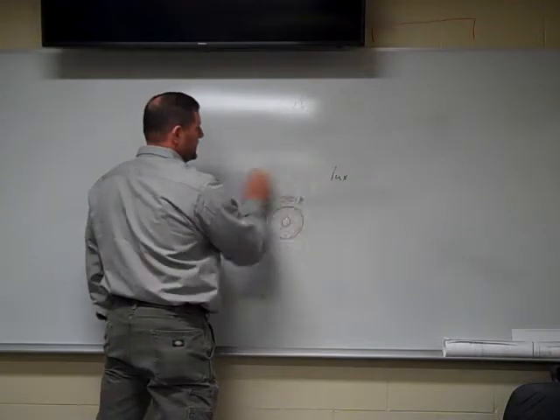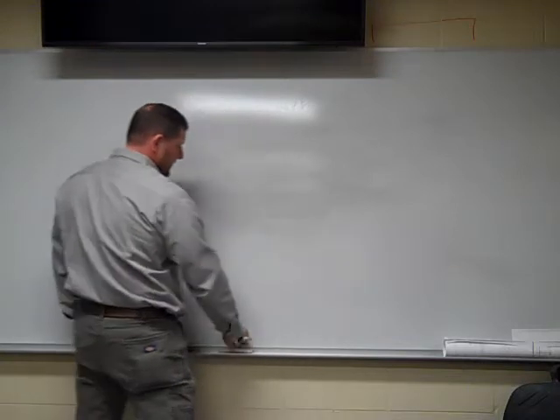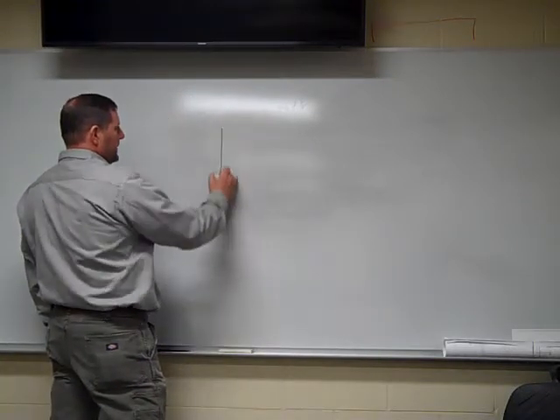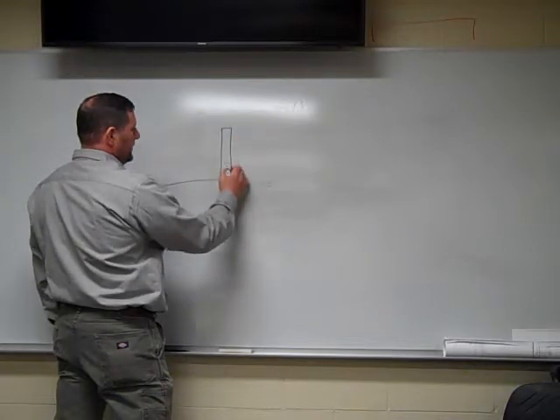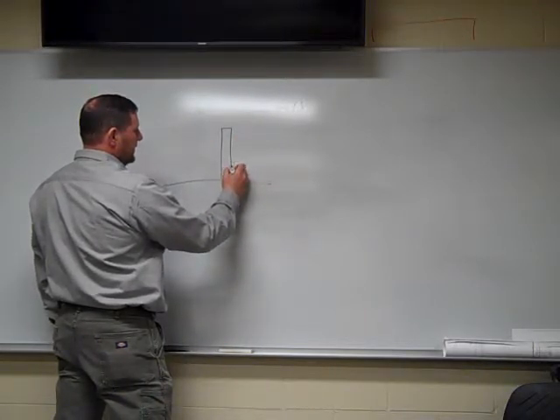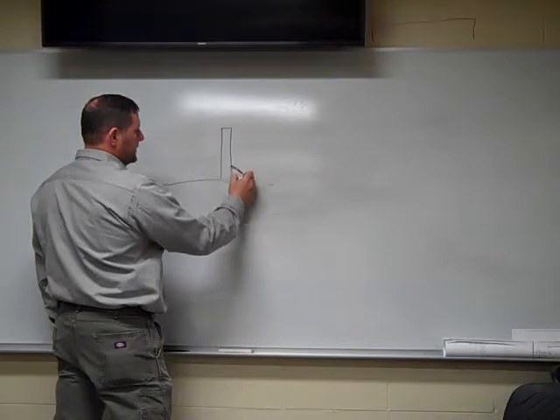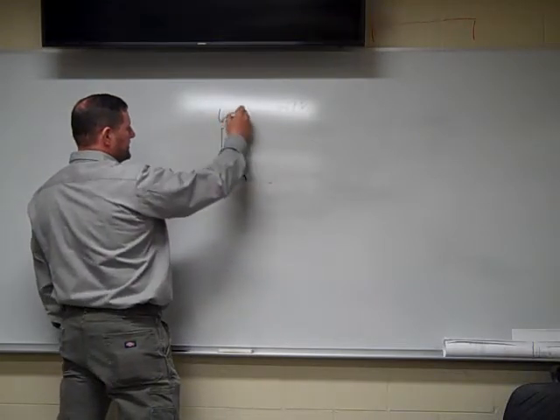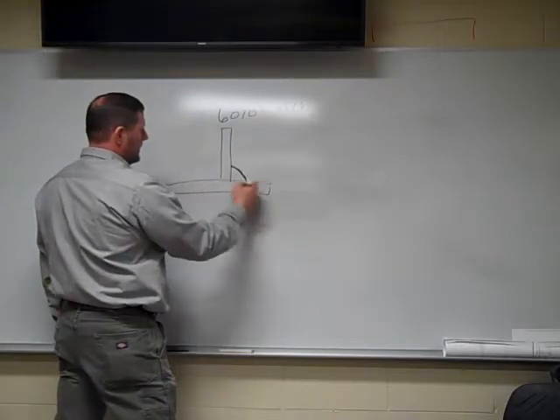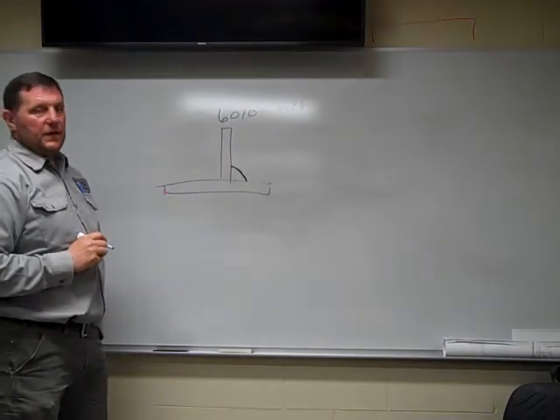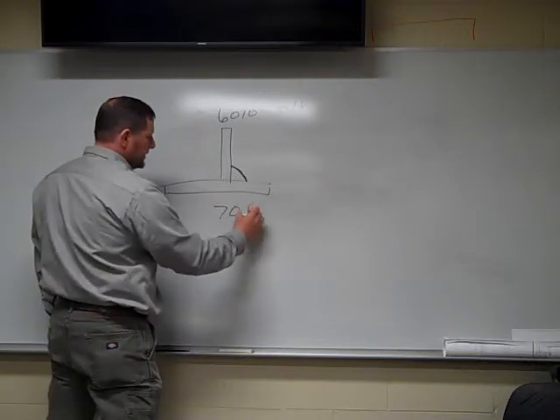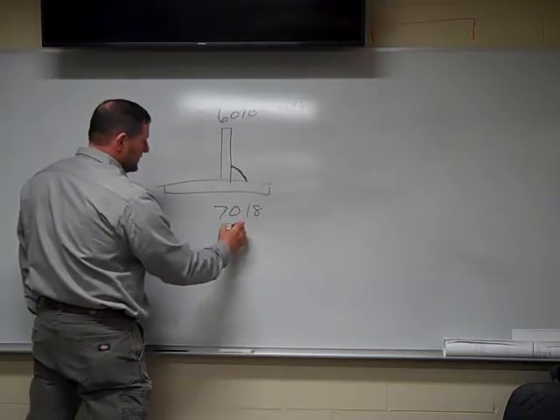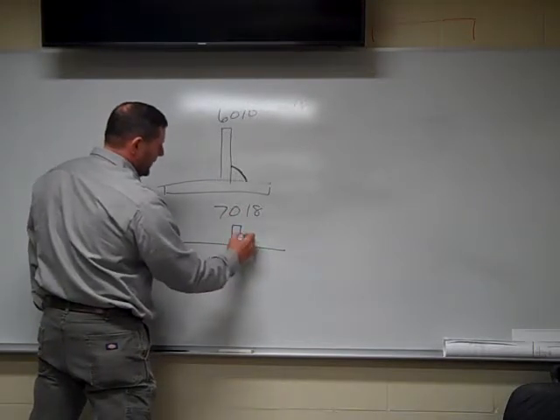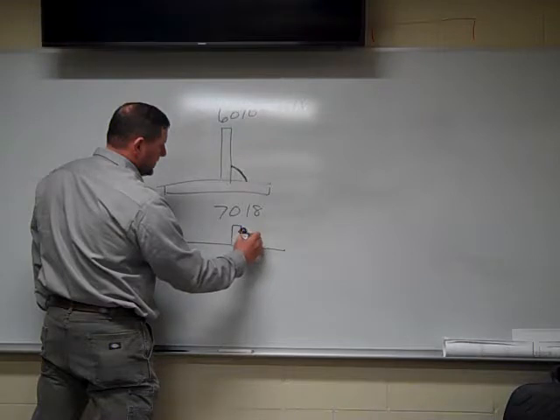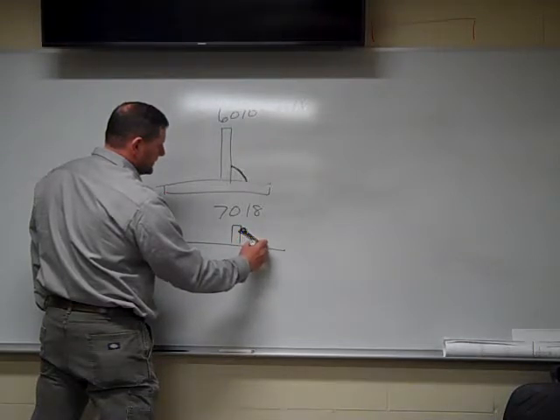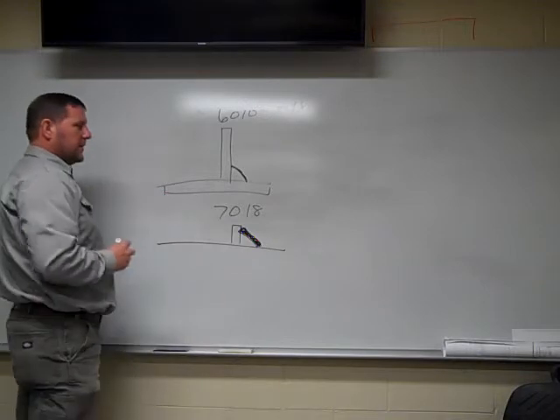Let's just take a look at something here. We'll show you why 6010 is different than a 7018. Here's a T-joint. Here's my weld, and then I have this very thin flux coating over my weld. This would be like a 6010. Now that weld's going to cool a lot faster compared to a 7018. So here's my T-joint. I put a weld here, and I'm going to have a lot more flux covering that weld because I have more flux on my rod.